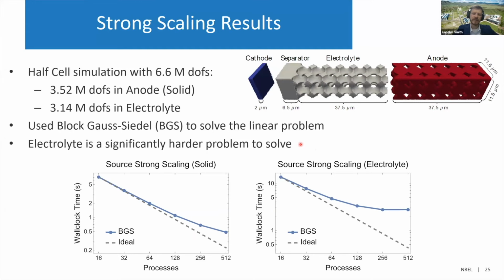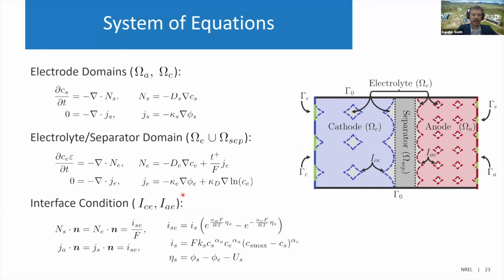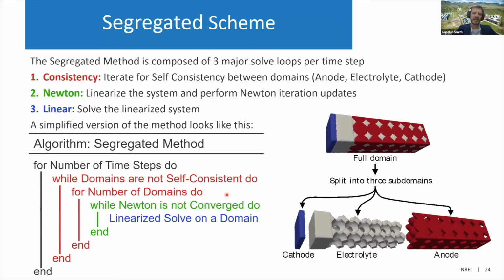One convenient thing that he found, and I don't have this in the slides, is to recast some of the transport properties which go to zero when concentration goes to zero. Some of the similar terms also show up in the governing equations. In this kappa D here, as concentration goes to zero, in the natural log term, you have a singularity in this equation. You can avoid that if you just recast your properties a little bit differently. And so that'll be in that upcoming paper as well. I think it would probably work well in a macro-homogeneous model.